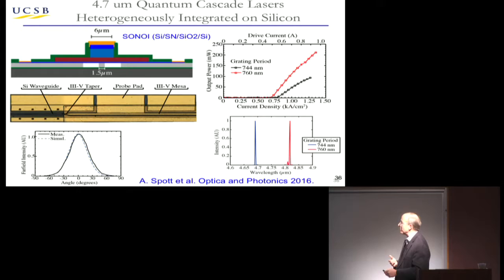So here's just an example of it. Looks just like the picture I showed before. There's an SOI material here, but typically now you need to get rid of the silicon dioxide. So it's a SONOI process. It's silicon nitride, so as to keep the lower oxide away from the mode. But this is what it looks like for a quantum cascade laser. And you can get hundreds of milliwatts out of these structures. You can make DFB lasers, which is what this is. So 2 DFBs at different periods. So it can work pretty well even at longer wavelengths.